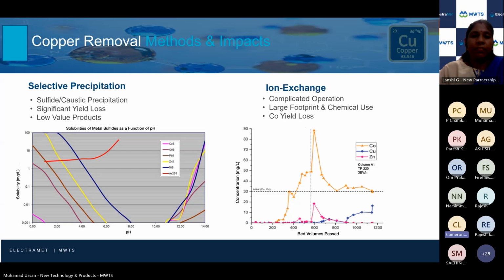And this also introduces a very high risk of yield loss of that cobalt if you don't do the exchange properly, if you don't have the right regen, if you don't recover the cobalt from that regen solution. So while it may work to get to the purity, it is just too much yield loss, and the operational burden from a labor and a process flow standpoint, and also a footprint, is just not really viable in our view. Next slide, please.